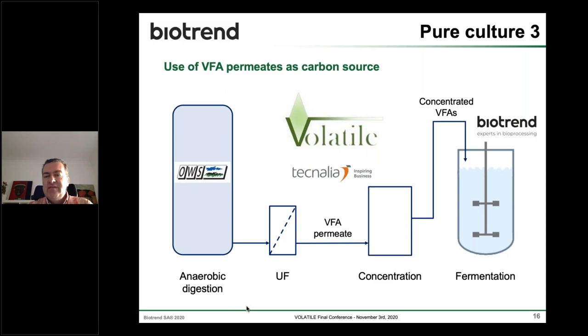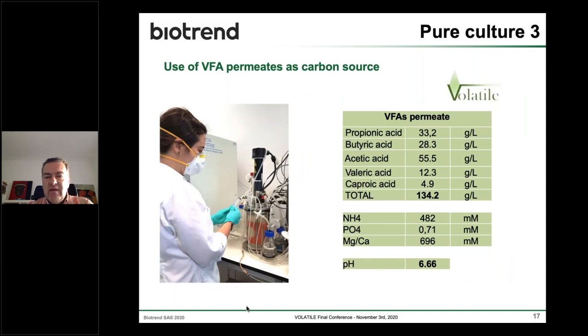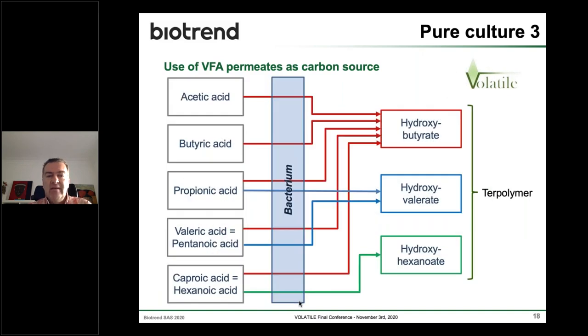And finally, coming to volatile, here we use concentrated VFAs in our fermentations. And in the streams and the material that we get, as you can see, we have quite a diversity of different volatile fatty acids, which is very interesting, as you will see in the next slide. Because depending on the type of volatile fatty acid that you have as raw material, the bacteria that we use will process these volatile fatty acids differently. And the different volatile fatty acids will originate different building blocks in the polymer. And at least theoretically, we could even produce terpolymers, meaning polymers with three different monomers.